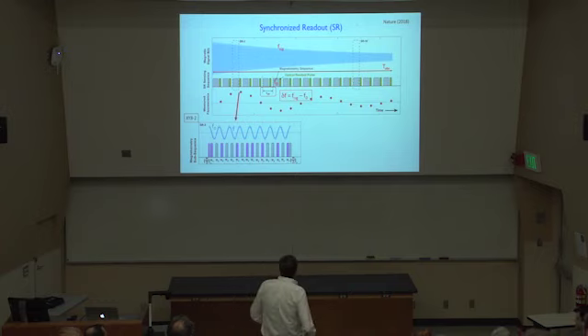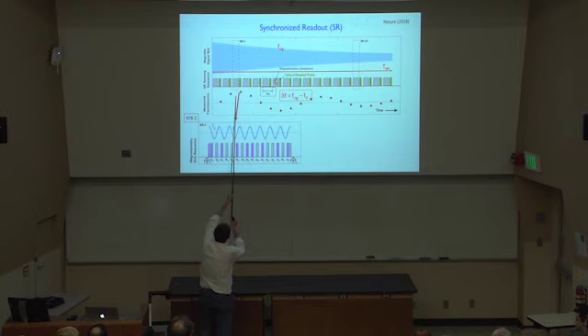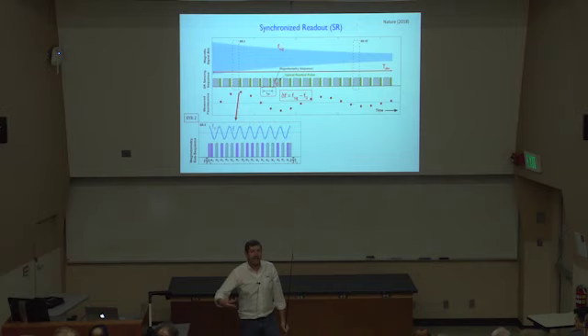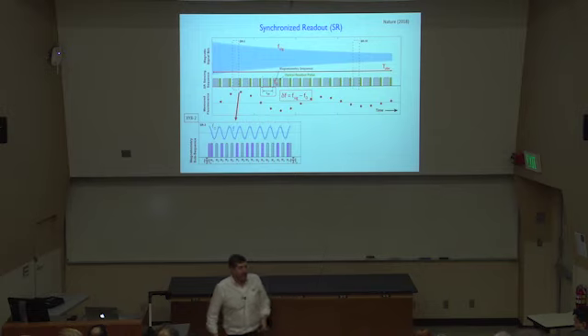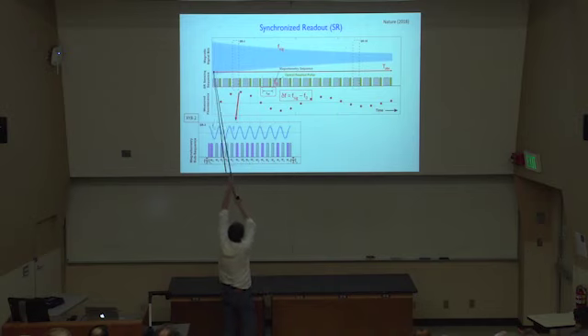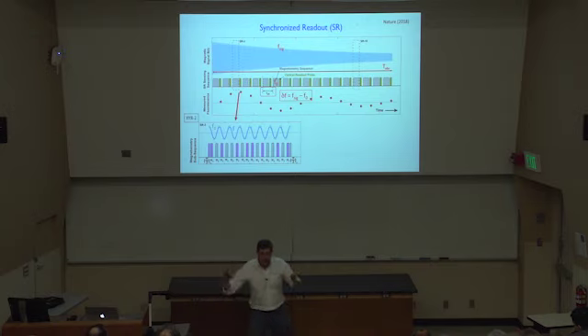The synchronized readout is that what people had done before is they'd make one such measurement, and then they'd do it again and again and again, where each measurement and when you began the measurement and ended it was independent of the last one, as if you didn't know anything. The idea is you now do a series of these where you're controlling when this signal starts and the order of these, but with a clock. So that, yes, there's going to be a little bit of information loss when you're not reading out, but the beginning of the next sequence is synchronized with the ending of the last one, so that the accumulation of the information will be in phase overall.